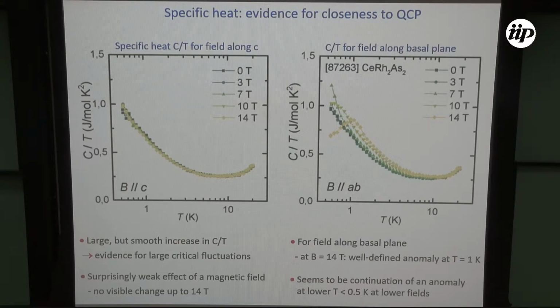Then you go to the most interesting part. You look at the specific heat. Here is C/T as a function of the logarithm of the temperature at low temperature, for field applied along the c direction, and here for field applied in the basal plane. You have a large, very smooth increase in C/T, and this is evidence for large critical Kondo-type fluctuations, or large critical fluctuations.